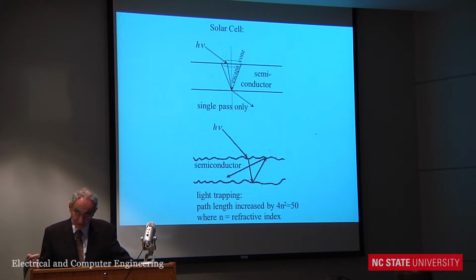Okay, so fine, maybe we'll use a direct band gap. Now what about absorbing the light? Well, here a problem comes up. And that is the light comes in, and most semiconductors have a high refractive index, so you refract toward normal, and then it goes right back out again. Hey, don't complain, at least you got a single pass. But what if you change something? What if one of the surfaces was rough? Here I show both surfaces as rough, but only one needs to be rough.